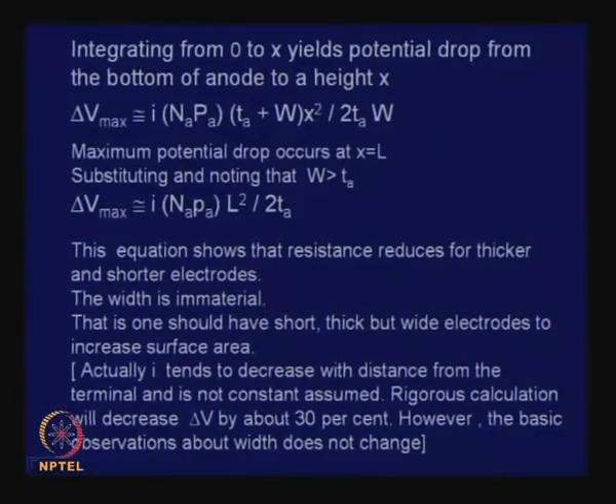So, obviously, the equation shows that the resistance reduces for thicker electrodes, this we know, it is always there for thicker electrodes, and shorter electrodes, the width is immaterial. So, what does the industry do? The industry simply cannot have very deep electrolytic cells. It does not mean they will be minuscule, there are some practical things after all. You cannot take an electrode which is only this high and 10 meters wide, no. But by and large the height has to be limited, width can be broad, because width is not adding to the resistance, and the electrode should be thick and wide.